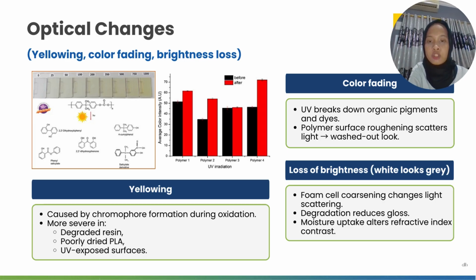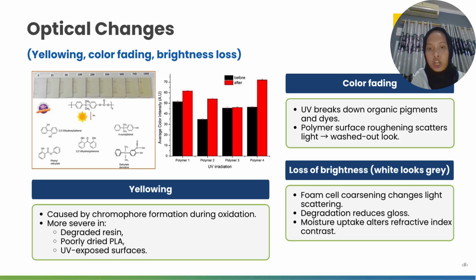Next is optical change, which is yellowing, color fading, and brightness loss. The yellowing is caused by chromophore formation during oxidation, and it's severe in degraded resin, poorly dried PLA, and UV-exposed surfaces. For color fading, UV breaks down organic pigments and dyes, and polymer surface roughening scatters light, and it leads to a washed-out look, like in this picture. And then the loss of brightness, where white looks gray, happens because foam cell coarsening changes light scattering, degradation reduces gloss, and moisture uptake alters the refractive index contrast.